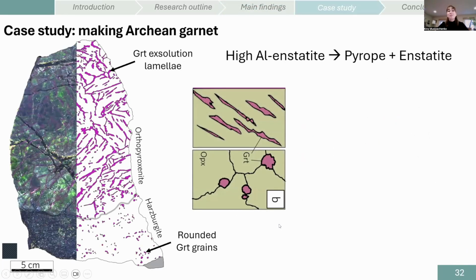So this is a fantastic sample from the Siberian Craton. It is quite big in itself. I would say it's at least 20 centimeters tall. And the really great thing about this is that it preserves two different lithologies smudged together. On the top here, we have megacrystalline orthopyroxenes with garnet exsolution lamellae. This part of the sample is just a scan. That's the natural emerald color of the enstatite. Looks fantastic. And then this is how much garnet lamellae we have in those orthopyroxene crystals. And the bottom part of the sample is a harzburgite with small rounded garnet grains.